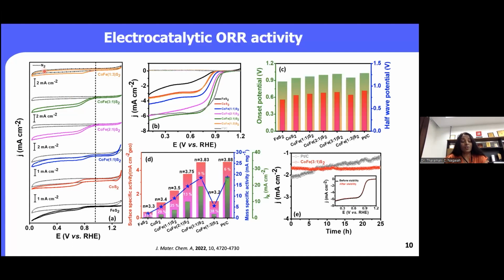As you can see, this dotted line shows the absence of oxygen. As soon as we purge the solution with oxygen, there is a steep increase in the reduction current. This indicates that our catalyst is active towards the oxygen reduction reaction. However, in order to evaluate the kinetics behind this, we have performed the experiments in hydrodynamic conditions, both RDE as well as RRDE.